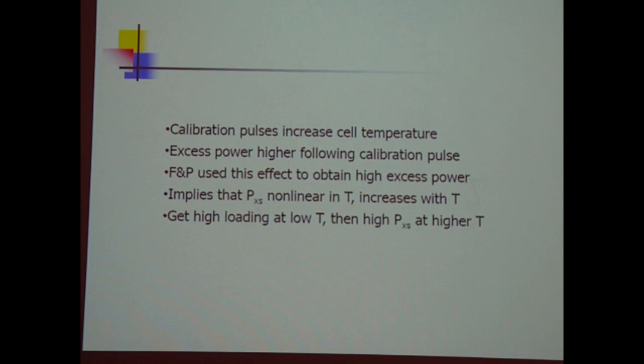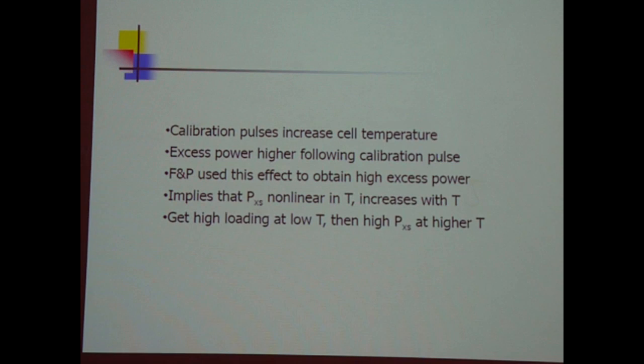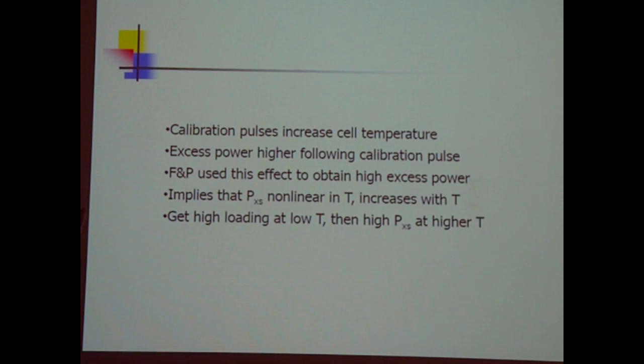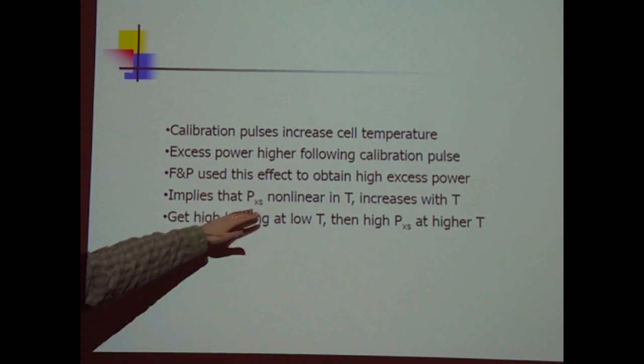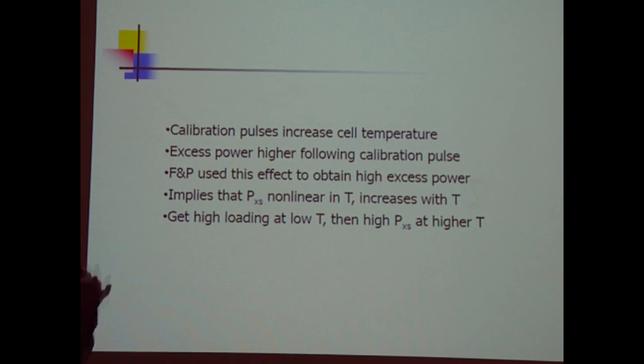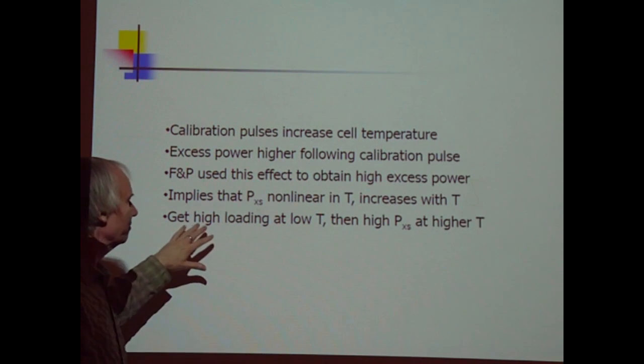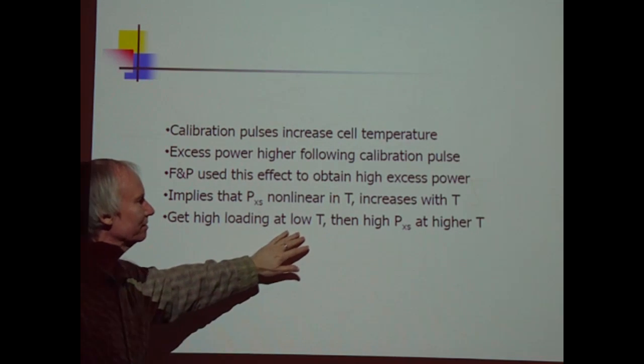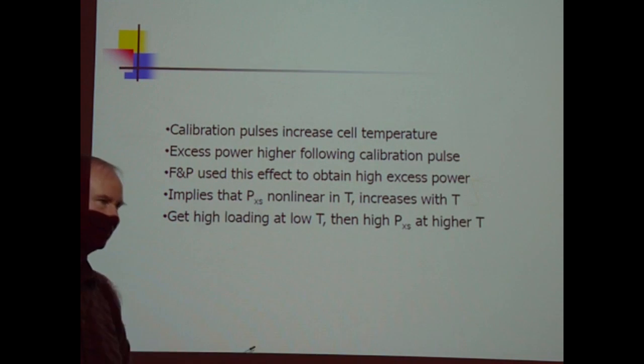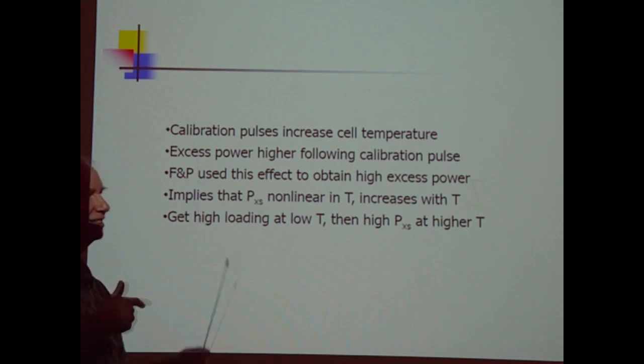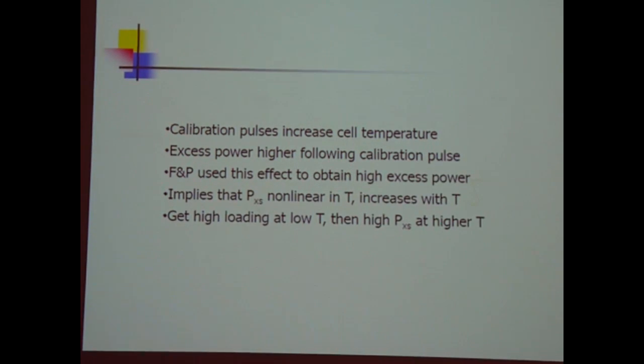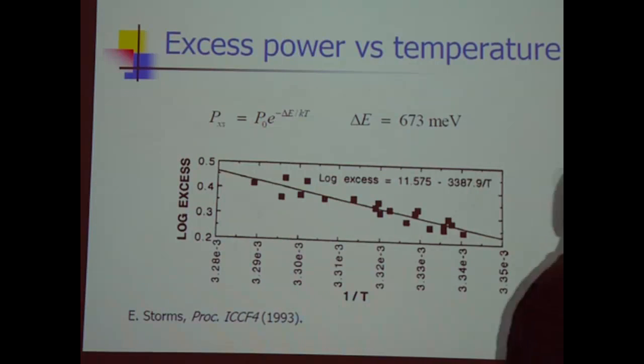So the question is what's going on and how do we think about it? Calibration pulse increases the cell temperature. Excess power is higher afterwards. Fleischmann and Pons used this as a way to develop a protocol that was much more effective in increasing the excess power in their cells. The implication is the excess power is nonlinear in temperature. Basically, you get more excess power at higher temperature. So in Fleischmann's protocol, you get the high loading at the low temperature, but then you get the high excess power at the high temperature. If you can maintain your loading, raise the temperature, then you can take advantage of this nonlinearity to get more excess power out.